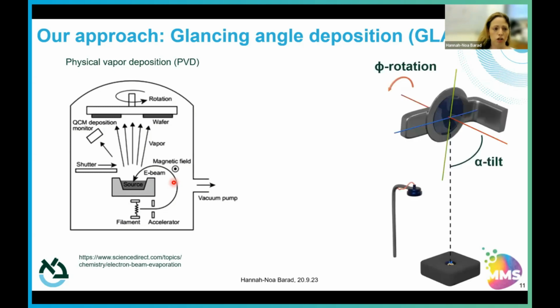In glancing angle deposition, there's a huge difference. So your source material versus your substrate or your sample is tilted to very high angles. And these are oblique angles, which is this alpha angle tilt. So this alpha angle is versus your source normal and your source material. So you have substrate and source material. This angle between them forms this alpha. And this tilt has to be between 80 and 90 degrees to be considered glancing angle. Anything from 0 till 80 is oblique angle deposition, just for clarification purposes.